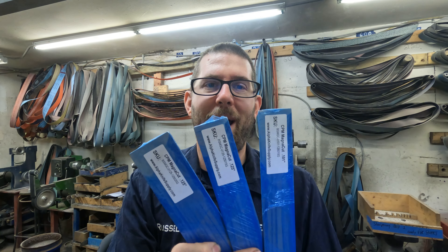The other thing I will be doing today: we got Magnacut in. This is a steel we have not previously worked in, but we're doing it for a regular customer who wanted a Magnacut knife. We're going to do a batch of — I think it's 24 knives — and send it off to Peter's Heat Treating, because this is a steel we cannot heat treat in-house. It needs an atmospheric forge and cryogenic processing — stuff we don't have the ability to do. Peter's did a great job on my Z-Finit and S35V.